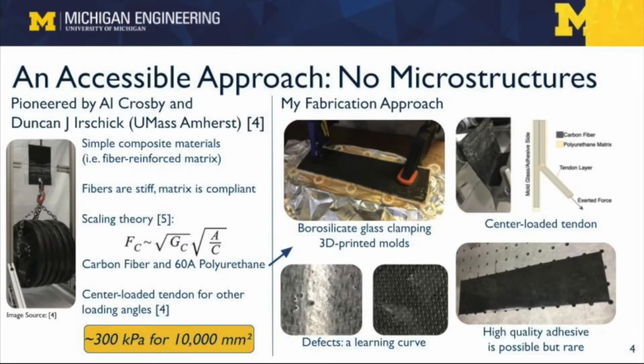For my experiments, I first had to fabricate the adhesives by embedding the carbon fiber in a polyurethane matrix. I used 3D printed molds to control the size and shape, and a borosilicate glass surface on which to mold the smooth adhesive surface. I added my center loaded tendon that prevents peeling at other loading angles as a second layer of carbon fiber bonded partially within the polyurethane matrix.